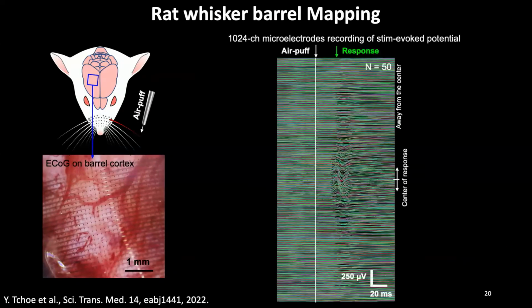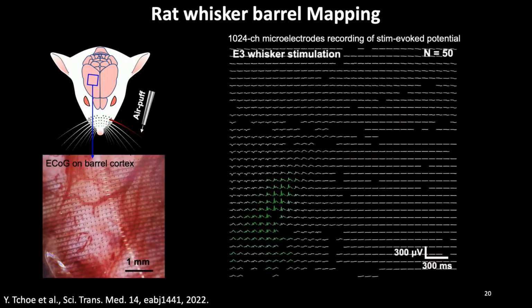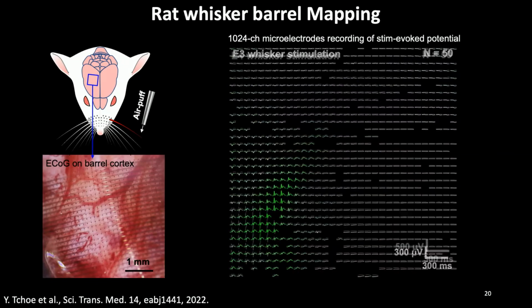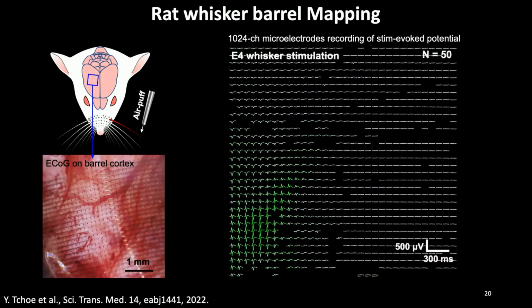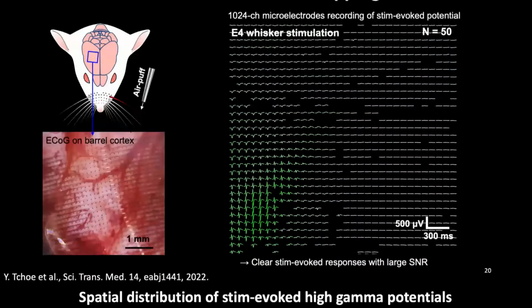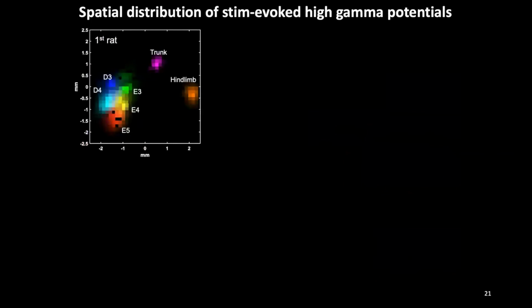When we look at the data from 1024 channels, you see a localized activity, and there is some delay also in waves or signals that appear at other channels. Now, if you distribute it spatially, this is for the E3 whisker, and then the E4 whisker, we have a shift in where the activity is mainly concentrated.